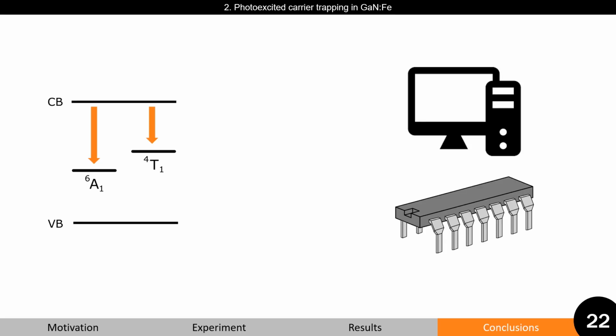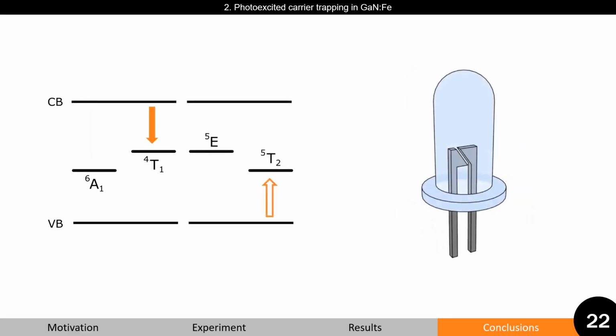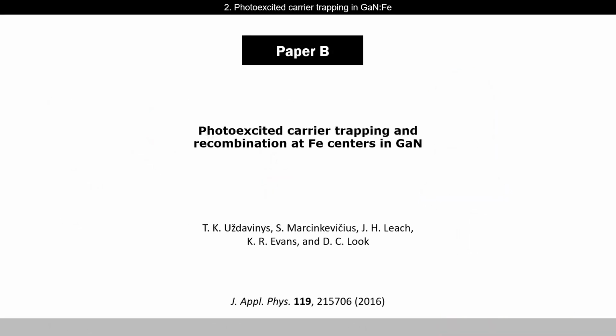For devices intended for low current densities, the capture coefficient to the ground state should be used. For devices aimed at ultra-fast optoelectronic applications, the capture coefficient to the excited state should be used instead. Second, if iron is introduced unintentionally, under typical LED currents, iron ions would be predominantly in their excited state, hence acting as efficient non-radiative recombination centers. Thus, for optoelectronic device applications, unintentional iron doping should be avoided at all costs. The results were summarized and published in paper B.